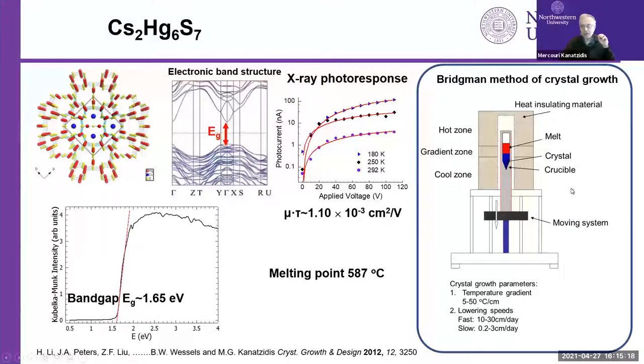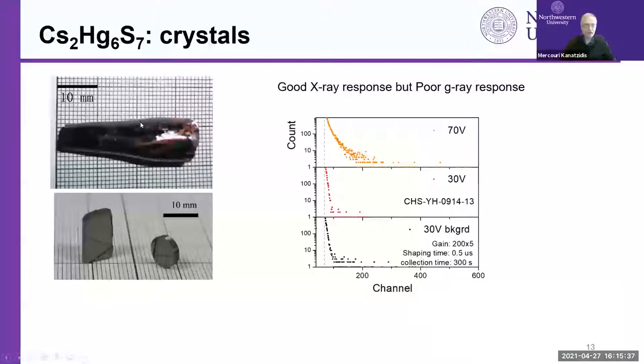We were able to use the Bridgman method of crystal growth, where you melt the material and you drop it through a temperature gradient. And when it freezes, if you do it right, you may get a large single crystal. It's not as simple, you have to spend some time on it, but it can work. So here's the crystal and it grows. We can get specimens like this. And this one, we can cut it and polish it. This is the gamma ray response on the right, and it's poor. The reason it's poor is because it has too high a dark current for gamma rays and too many defects. However, it does respond well to X-rays, and it is promising for X-ray applications.